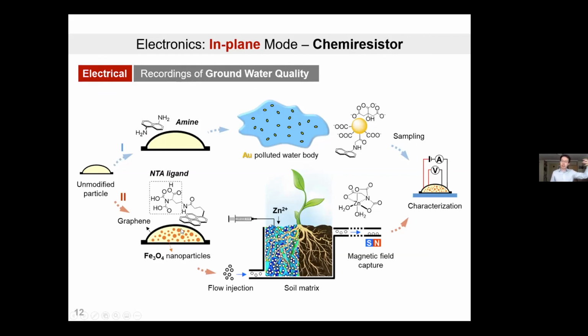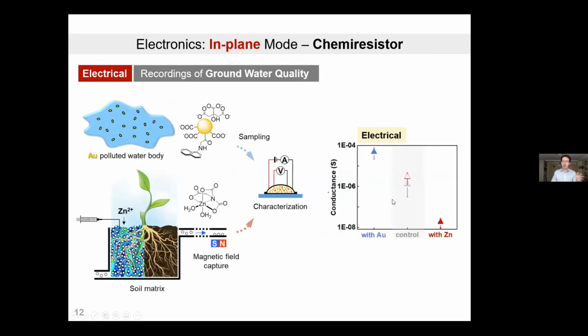These little magnets will traverse through a soil matrix. When they come out on the other end, you can use a strong magnet to harvest them back inside your microfluidic stage, and then later test them under a probe station. So to cut the long story short, these can be made into very sensitive and selective chemical sensors using the chemical resistivity of the 2-dimensional materials.